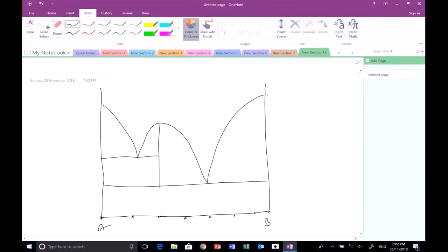So you're going to take this composition A, and you'll probably do a series of compositions across here to get the lay of the land, to see how this stuff performs. And you're going to heat them all up, same temperature and time conditions, so you get a level playing field and see what happens. So this is the temperature you're going to choose to kick things off. So there's an isotherm across there. And we're going to have this composition and this composition, this, and this. And we can read it right off the phase diagram what's going to happen. Actually, from this you can construct the phase diagram. You need to do a bit more, but it's the starting point.